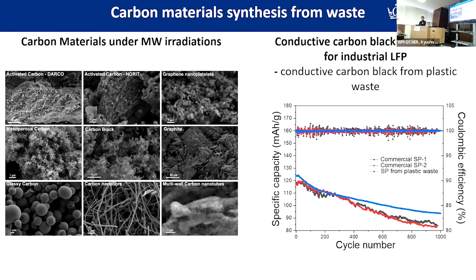We also tried to see if we could tune the catalyst to produce a different kind of carbon material, for example, the carbon black that is widely used in lithium ion batteries as a conductive additive. And the answer is yes. By varying the catalyst, we successfully produced carbon black, and we have tested it in a lithium ion battery, and it shows better performance compared to the commercial SP, a superconductive carbon black. That is a good sign, because it means the carbon produced in the microwave has a very good structure, and that can be used in different applications.